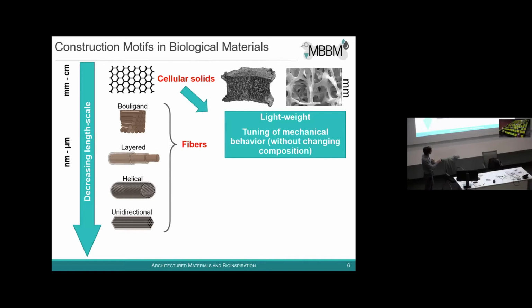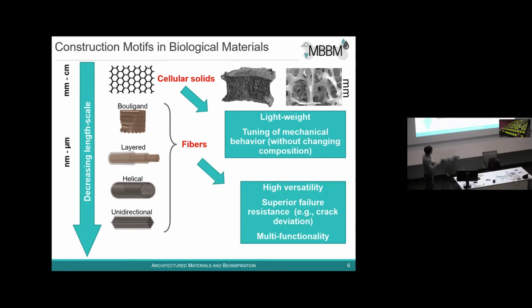mechanical role. But what is taking the load, which is transmitted across the vertebra, are those small structures which have a length of about 1 millimeter, which are called trabeculae. So these are stiff beam elements which are arranged in different ways to take up the load of our bones. And when you zoom in even more inside this structure at the micrometer length scale, you see that one trabecula is actually not a homogeneous material, but is composed of fibers. These are so-called mineralized collagen fibrils, which are arranged in bundles, and also these have different directions depending on the position where you are in the bone and on the loading requirement.